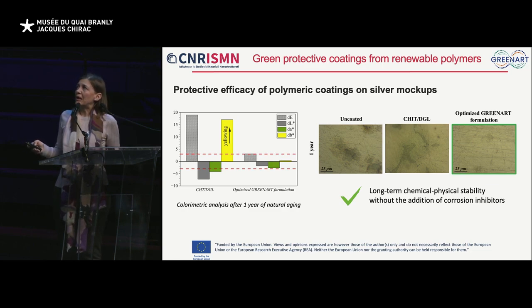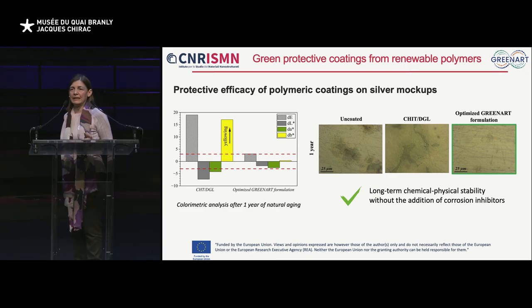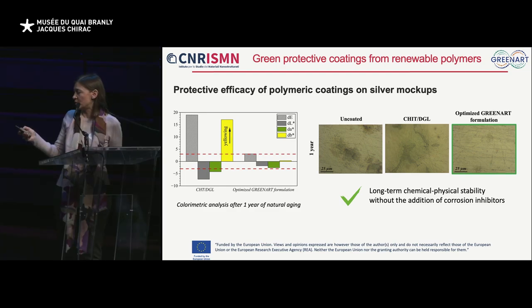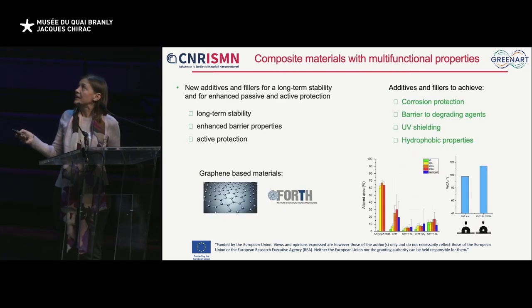But most of all, it is worth noting that from colorimetric measurements we can see that we can avoid the yellowing, because with the previous formulation we can observe a significant increase of the parameter which takes into account the yellow component. Here it is significantly lower, and the same is for the delta value, which is significantly lower. So we can improve the stability over time, and this is also quantified.